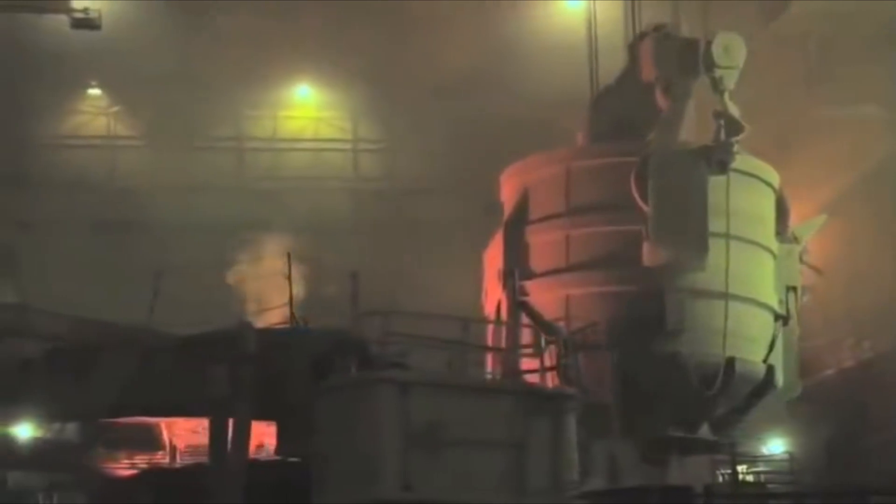The charging bucket is moved to a position directly above one of the mill's two twin-shell EAFs. The scrap is then released into the furnace, creating some real fireworks. The reason for the explosion is that a portion — about 40 tons — of each heat of molten steel is left in the furnace to keep it hot for the next heat, saving time and money. Once the scrap and pig iron are loaded, the roof of the furnace is closed, and three large carbon electrodes are lowered through an opening in the roof. The rods circulate, or arc, up to 115 million watts of electricity to melt the scrap at a temperature reaching 3,000 degrees Fahrenheit. The power is on for about 35 minutes to complete the melting of each heat, which is a good reason why our monthly electric bill is about 7 to 8 million.